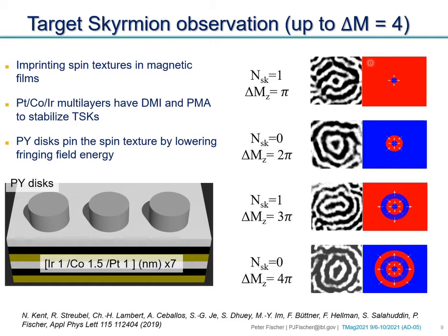And what we found were spin textures, and I just want to draw your attention to the full circles, not the broken ones. You see there's one white-black circle here. This means the magnetization makes one rotation. This is the regular skyrmion. And then you see two of them, a 2 pi rotation here, a 3 pi rotation, and underneath about 400, 500 nanometer disk structures up to about a micrometer.